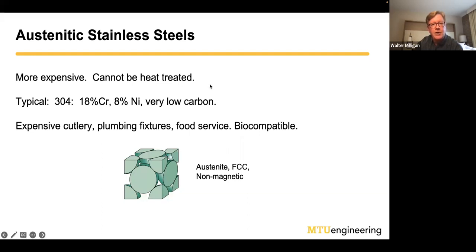And in this particular case, you want to have very low carbon because if you have carbon in these steels, they tend to form a chromium carbide phase at the grain boundaries, and that ends up giving you a corrosion problem. So for example, if you're using this for a plumbing fixture, you can actually get pinhole leaks in your plumbing fixtures because of corrosion if you have carbides in there.